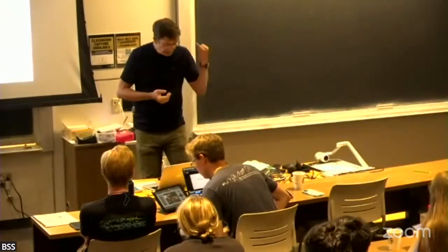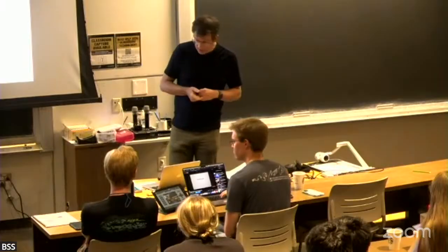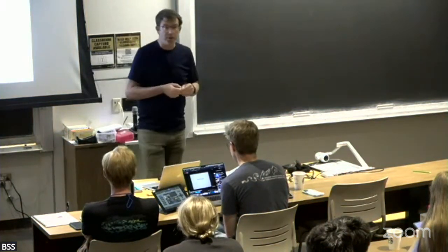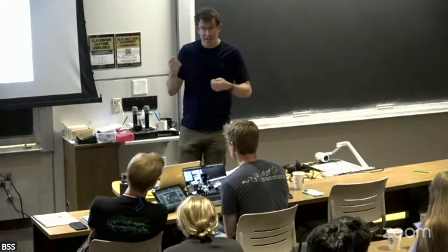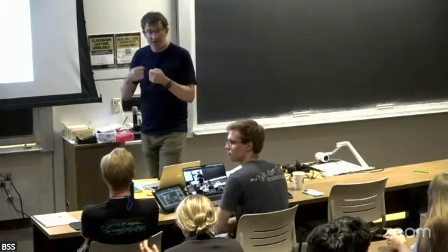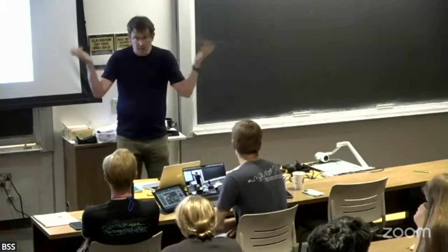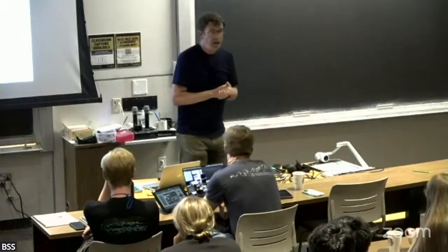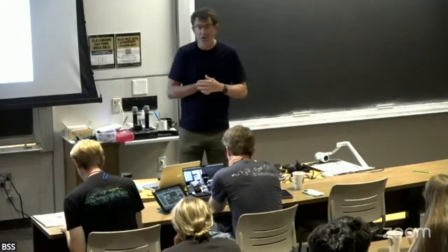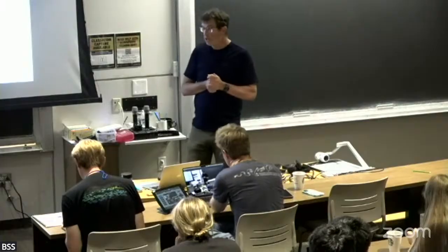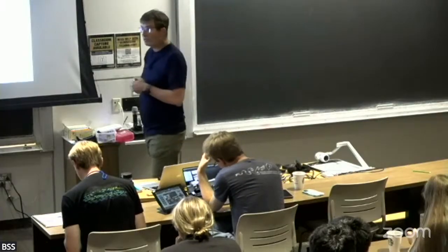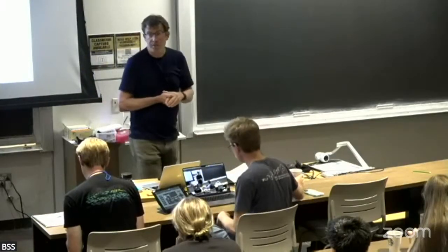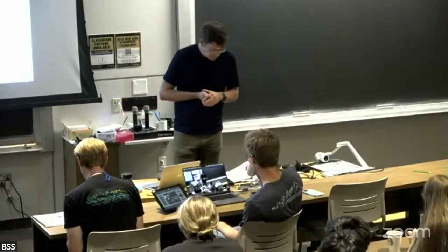Okay. The other thing that I had emphasized was we have these response functions in the linear response, but it's important to recognize they're complex response functions, right? They have real and imaginary parts. They're not separate things. They are characteristic of one global response function that is going to be useful for characterizing systems. And for some systems, for instance, we want to know the imaginary part. That carries more information than we might have considered otherwise. In superconductors, for instance, the imaginary part of the complex conductivity is the thing that we actually care the most about.